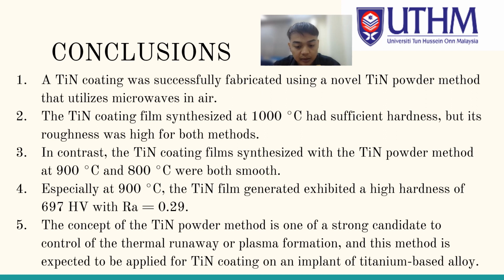The TiN film generated exhibited a high hardness of 697 HV with Ra equal to 0.29. This result demonstrates that a hard and smooth TiN film can be obtained using the TiN powder method by decreasing the energy of the exothermic reaction between the raw powder and air, which can prevent excessive TiN coating progress.